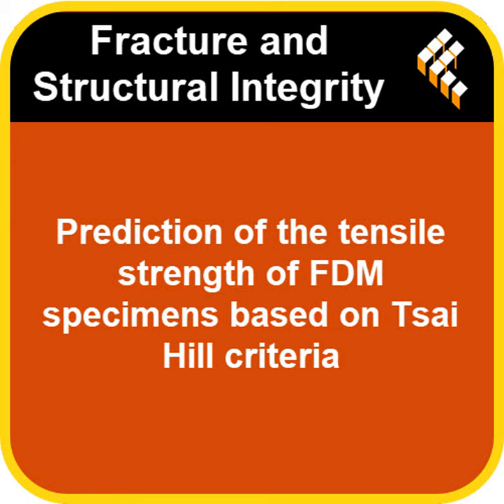Layer by layer. Okay. Now, this study was super precise about it. They used a specific Prusa printer with a 0.2 millimeter nozzle, which is pretty fine. Yeah, and they carefully controlled the temperatures. The nozzle was at 230 degrees Celsius to melt the PETG properly, and the print bed, where the part is built, was heated to 80 Celsius. That helps the layers stick together well. Gotcha. So it's all about laying down those hot plastic lines just right.